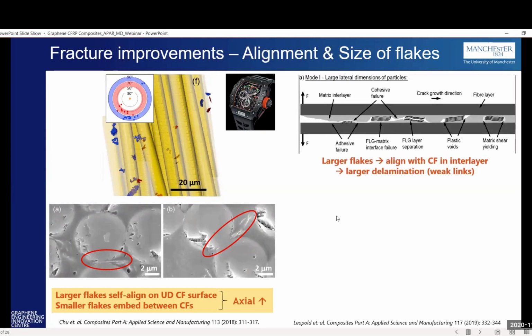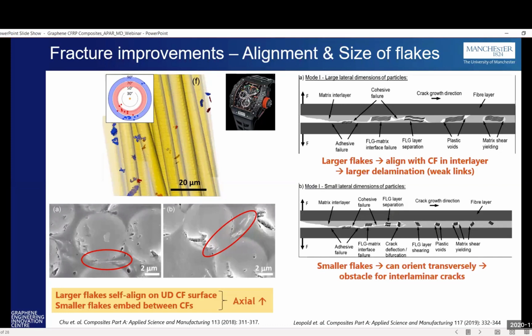Keeping the same theme, as I mentioned, the larger graphene flakes align in between the laminates. So when a crack propagates, because of the larger graphene flakes, the few-layer graphene can separate, and this can lead to a weaker deformation. But smaller flakes can align in any direction, or in a three-dimensional way. So when a crack propagates, it has to go through a lot of routes, and these small flakes can act like an obstacle for the cracks. The take-home message is that smaller dimension flakes work very well for carbon fiber reinforced plastics, rather than larger flakes, which are typically the case for rubber and plastic based materials.